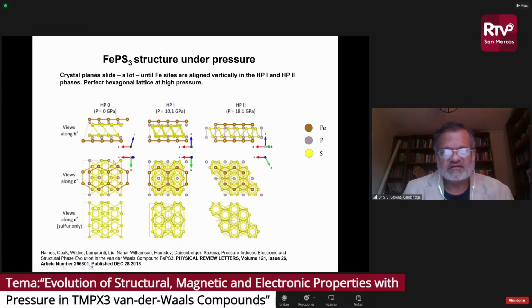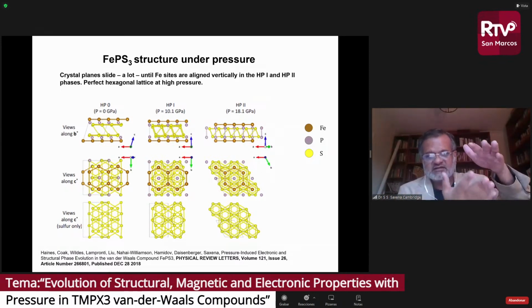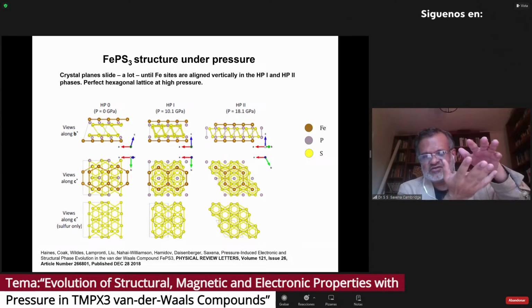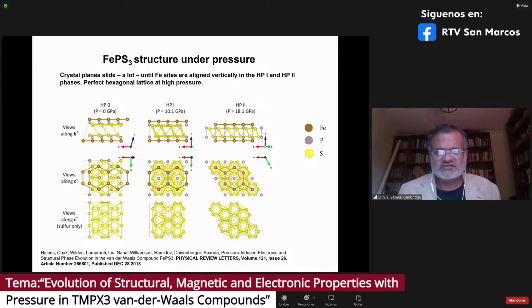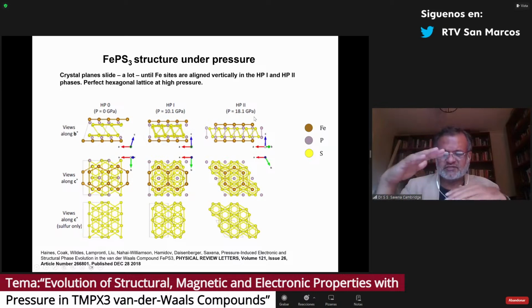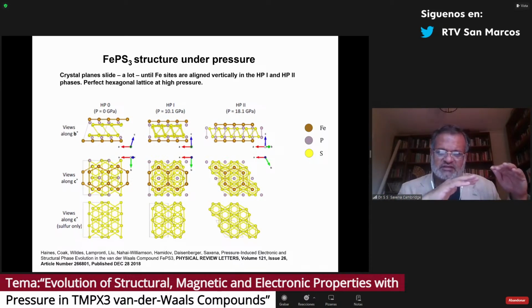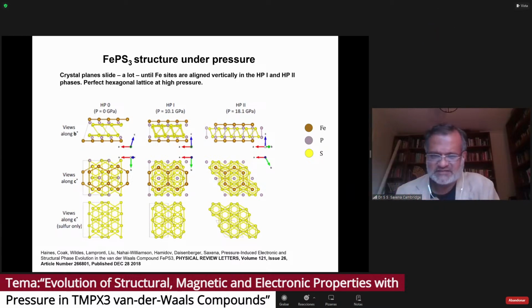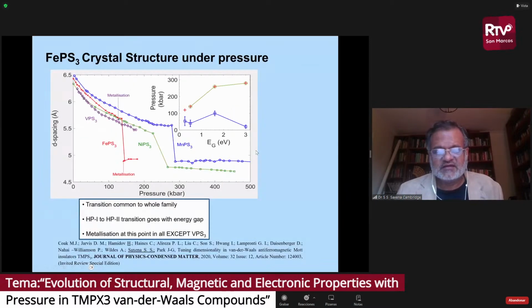Oops, what's going on here? Yeah. So the results show you how at zero pressure these are layers, and then you apply pressure, they slide and resettle, and then you go to yet higher pressures, they go through a transition where the bonds reform. So we can go from zero pressure to about 100 kilobars to nearly 180 kilobars. We can see how the material goes from being a magnetic insulator to a kind of metal, and that kind of metal we'll discuss a little bit more. So this work was published in 2018.